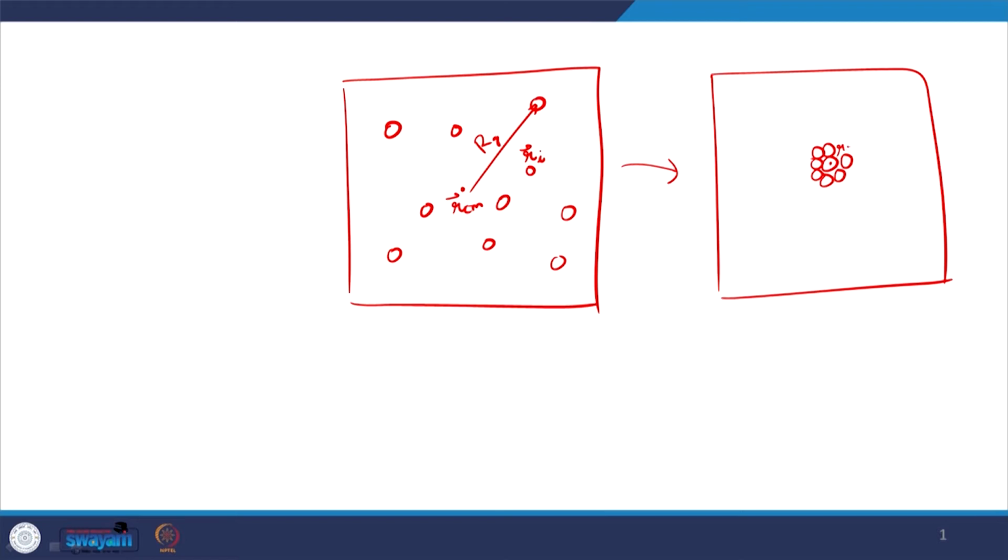In here, all the molecules will be closer to the center of mass. So, in this case you will have a smaller Rg in comparison to this case where you have the larger Rg. So, not only a molecule size, if I do it over the entire system, the Rg can also contain information regarding aggregates that are forming. When the Rg is decreasing, that means that we are having some kind of aggregation happening in the system.